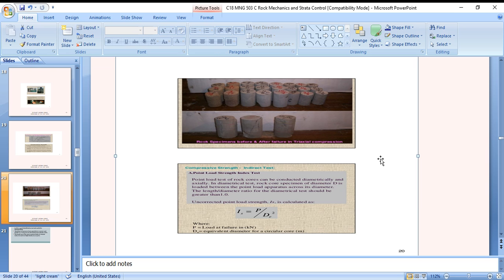In a diametrical test, a rock core specimen of diameter D is loaded between the point load apparatus across its diameter. The length to diameter ratio for the diametrical test should be greater than 1.0. Uncorrected point load strength is calculated as Is equal to P by D squared, where P is the load at failure in kilonewtons and D is the equivalent diameter for the circular core.